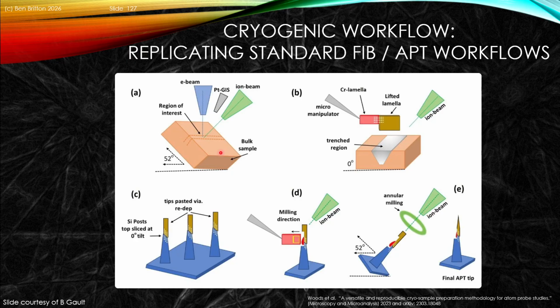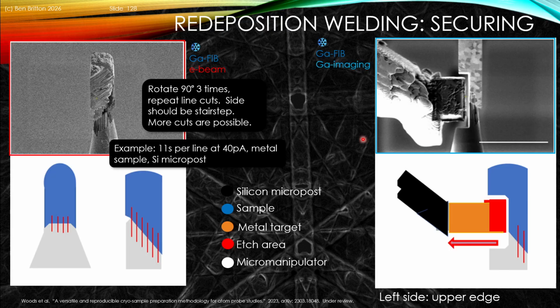And there's some details that are important for how the manipulator and effectively the process has worked. One of the major bits here is that the welding process has to be changed, and so if we're doing cryo-FIB work, we might use an alternative welding strategy. The alternative welding strategy in this case is with a small object, you can basically do a series of line cuts in the object, and when you do the line cuts, the redeposition enables you to lock the two materials together. And so these are the line cuts that are presented in the object to enable you to weld this.